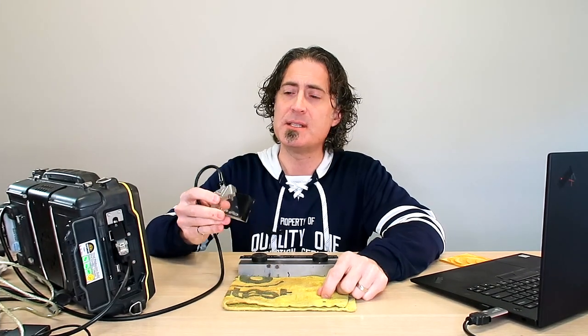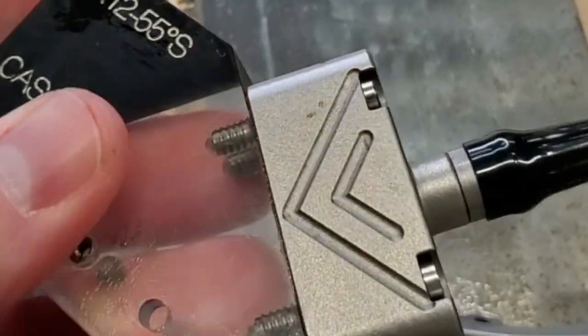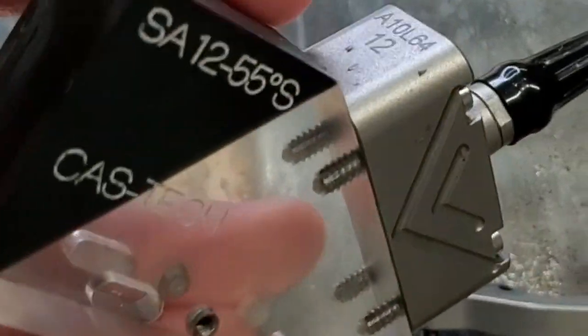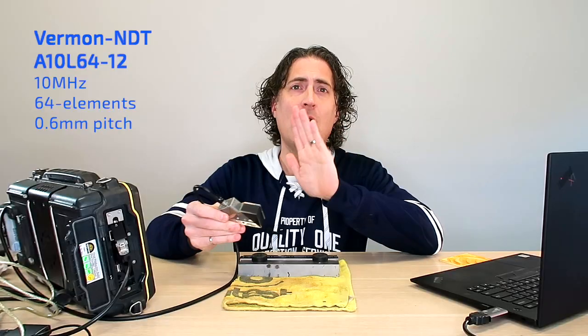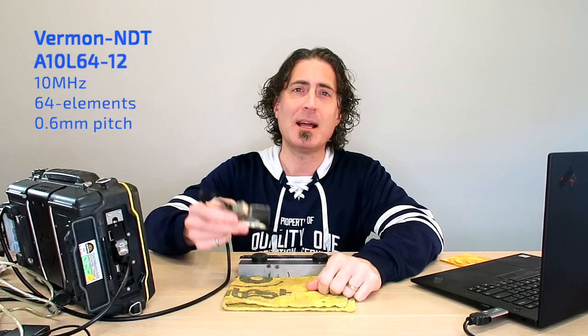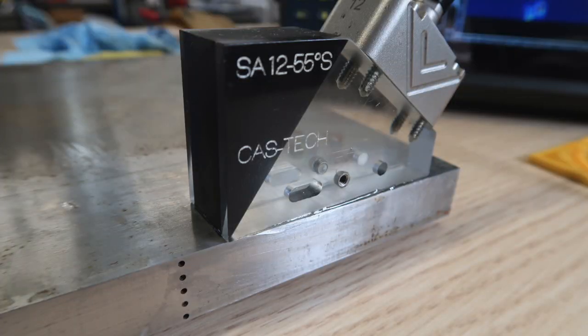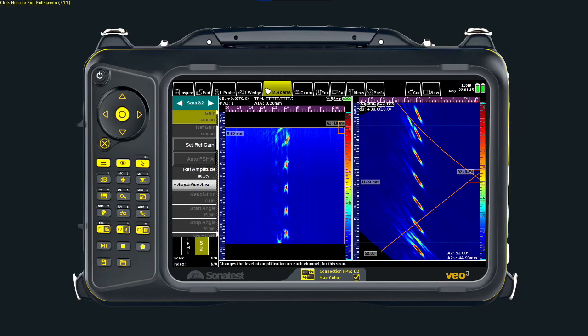We'll test it on some simple targets. First, I'll use this Vermon NDT 10 megahertz 64 element A10L64-12 transducer on this wedge, and we'll stand back a little bit from the targets just to pretend like we're on a real weld. Here I've got a stack of side drilled holes. On the left is TFMi and on the right is regular phased array. Those holes are really close to the surface, but at 10 megahertz, the resolution is really nice.